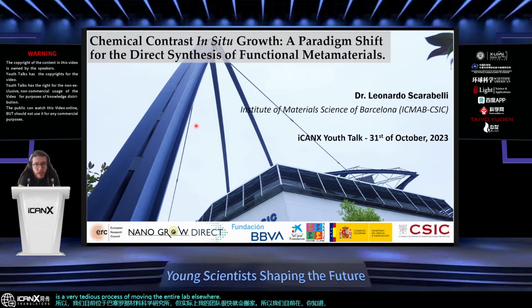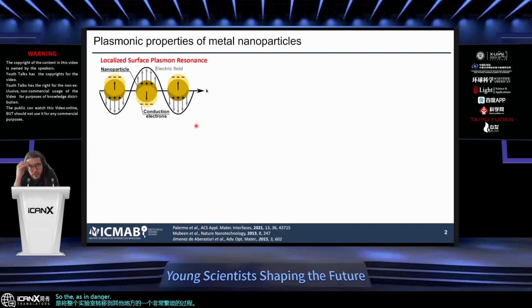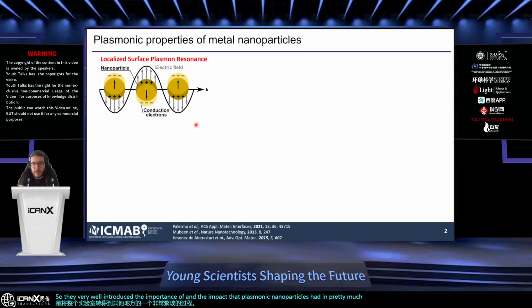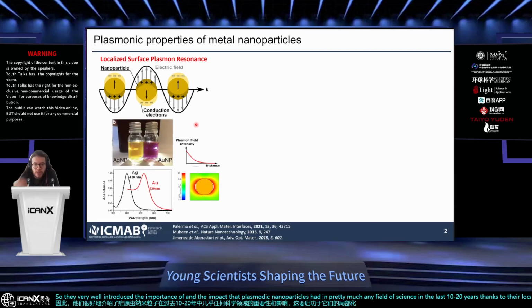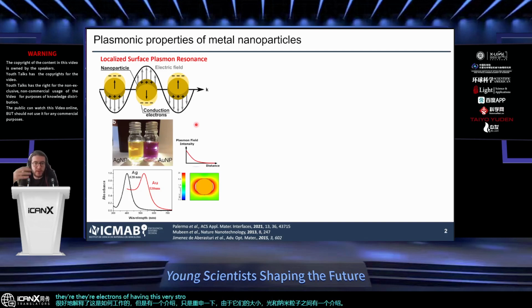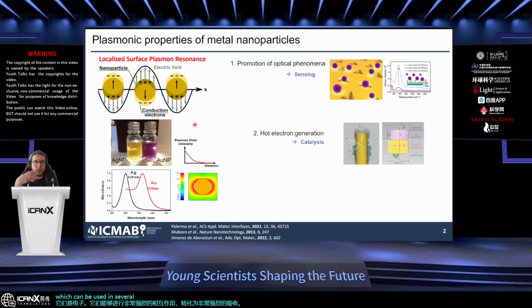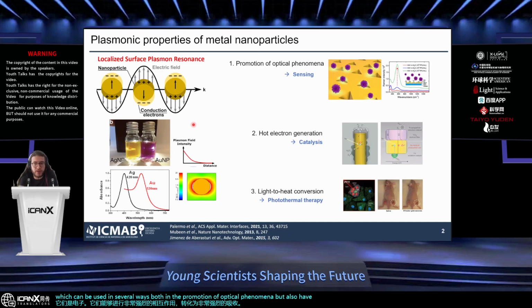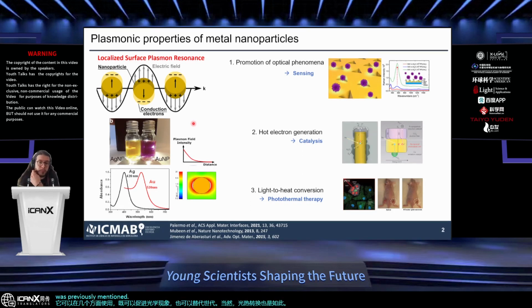But as Dayne very well introduced, the importance and the impact that plasmonic nanoparticles have had in pretty much any field of science in the last 10, 20 years, thanks to their localized surface plasmon resonances. He did a very good job at explaining how this works, but just to reiterate, there is an interaction between light and nanoparticles, thanks to their size and their electrons. They are capable of having this very strong interaction, which translates into very intense absorption, which can be used in several ways, both in the promotion of optical phenomena, but also hot electron generation, and of course light to heat conversion, as was mentioned in the previous talk.